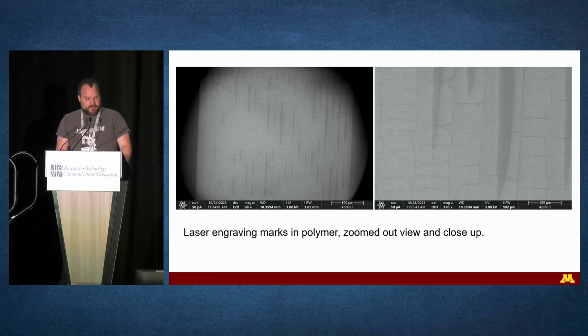This was from a local company. They were doing laser engraving on a polymer. This was actually particularly hard because you can see these squares with the naked eye, and they're almost invisible in the SEM. They're exceptionally shallow. I think the topography that's being viewed there was approximately 5 nanometers or less.